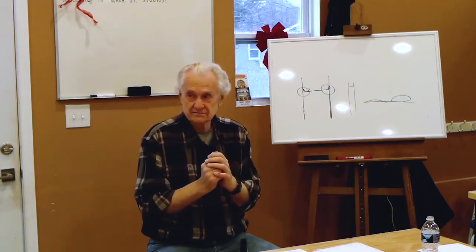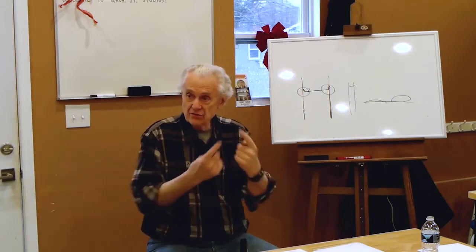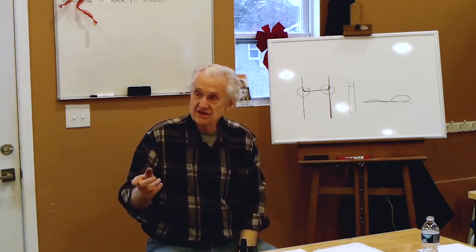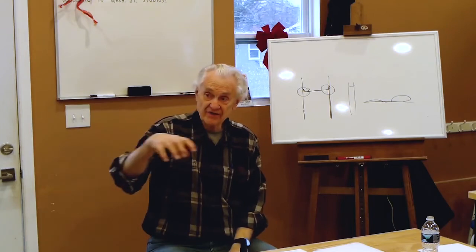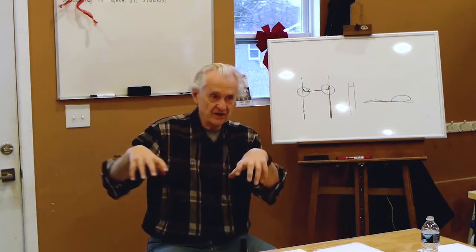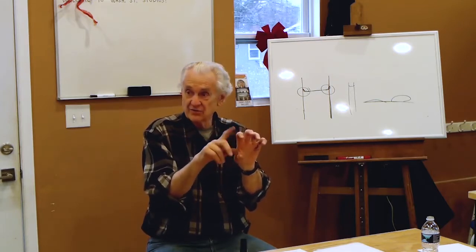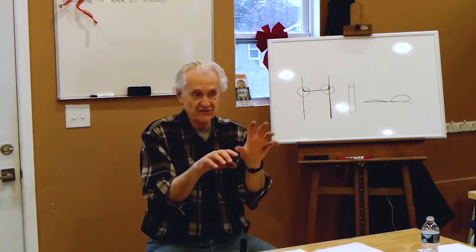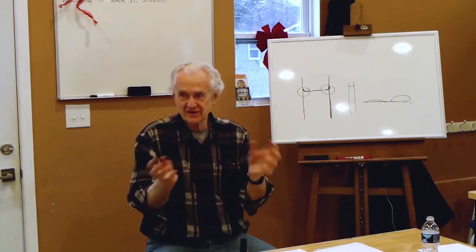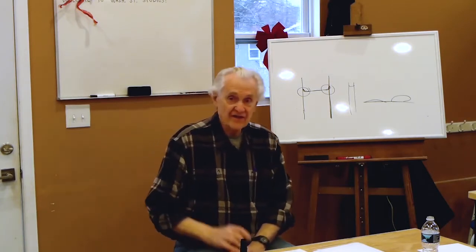So that's why you want to dry it slowly. You want to give enough time for the water to move to the surface, so it doesn't come in real quick. And especially so that one part doesn't come in quicker than another, which is the really key thing. Because if one part is shrinking more than another, you're going to get a crack between those two parts. If one part isn't moving and another part is moving, that's a physical impossibility, so you're going to get a crack.